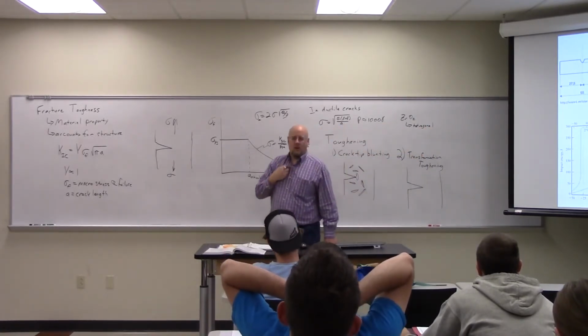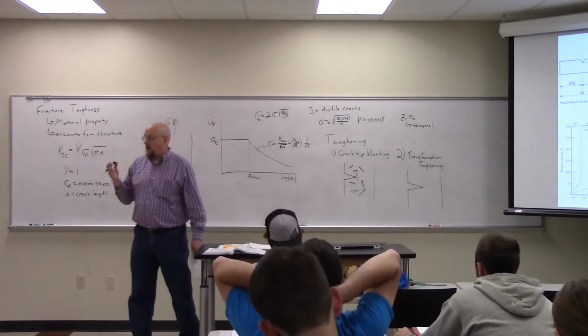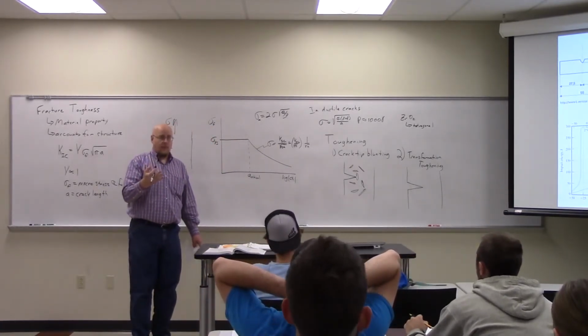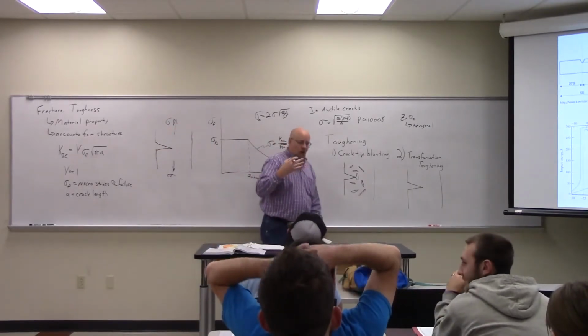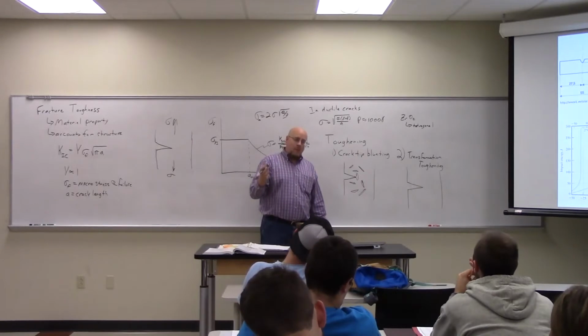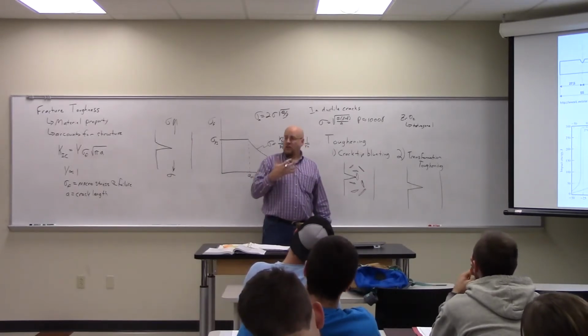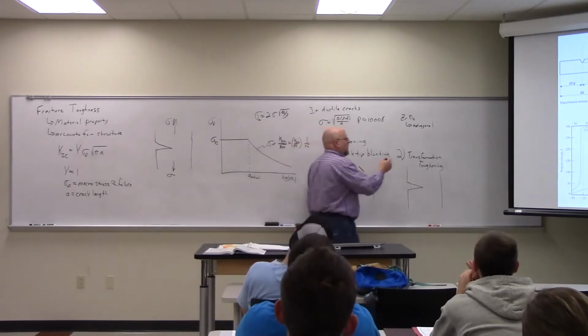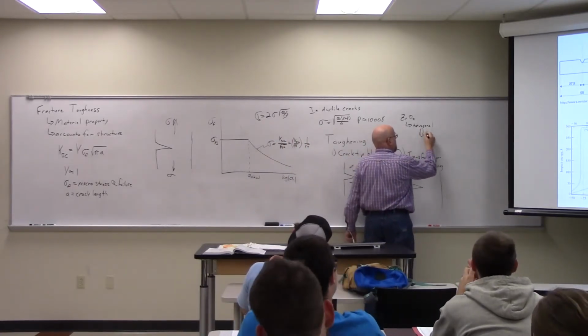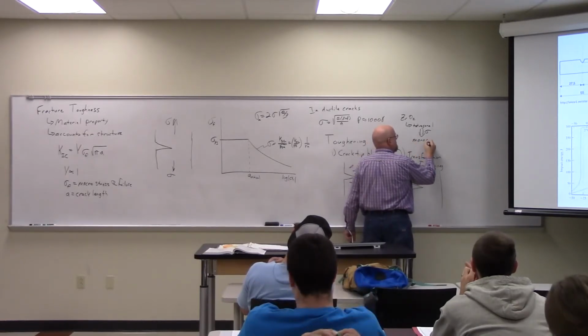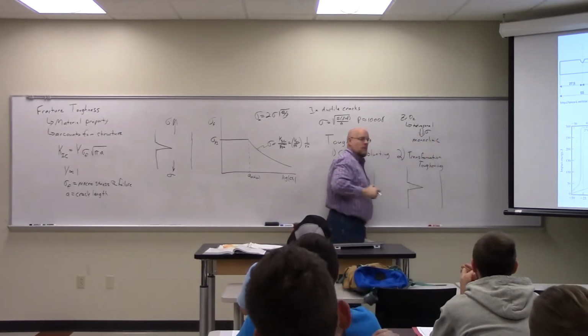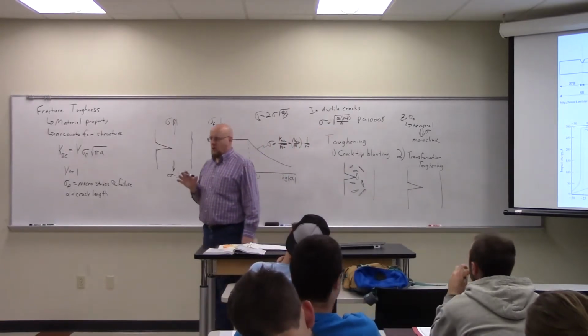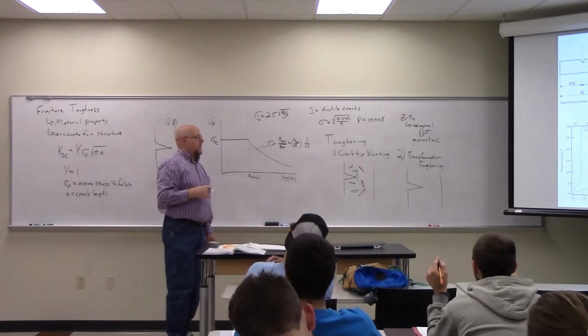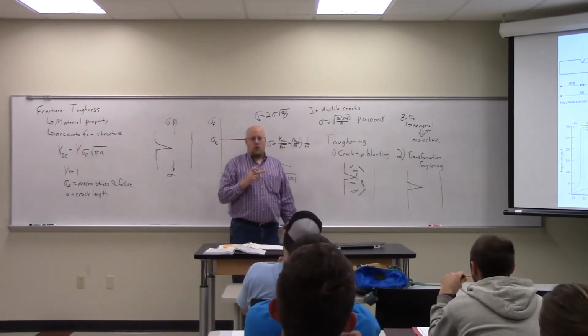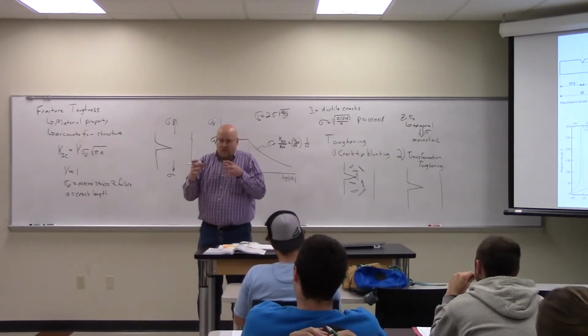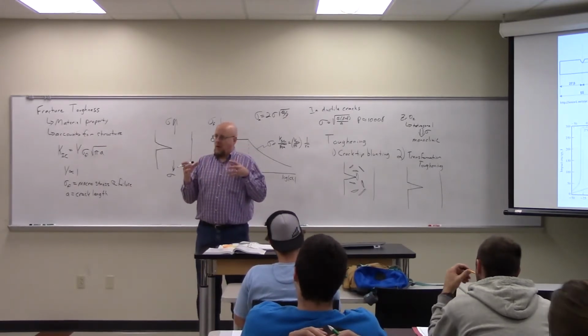That's its normal state. But when you stress it, very much like tin, remember we talked about twinning in tin, when you stress it, it accommodates the stress, it deforms, not by creating twins, but by actually changing its crystal structure completely. So under presence of stress, it actually becomes monoclinic. So it actually changes crystal structure when it's stressed above a certain value. But the monoclinic form has a lower density. The packing of the atoms is not as tight in monoclinic as it is in tetragonal.